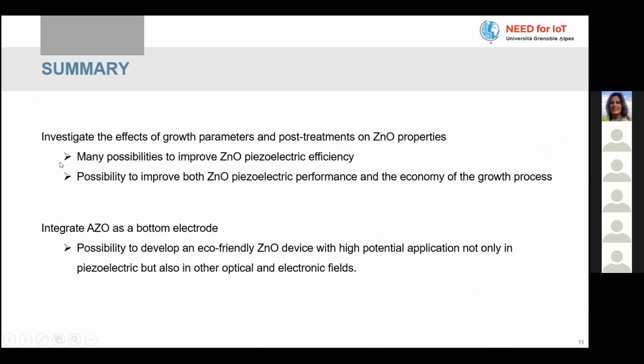So in summary, until now we have investigated different parameters of zinc oxide, and it gives us many results and possibilities so that we can improve the zinc oxide piezoelectric efficiency. The results also show the possibility to improve both the piezo performance and the economy of the growth process. When we integrate the zinc oxide with AZO as the bottom electrode, the result also shows that we can develop a zinc oxide based piezo device which is eco-friendly and not limited to piezo application. The result also shows that this device can have potential for other application fields like optical and other electrical fields. So thank you for your attention.